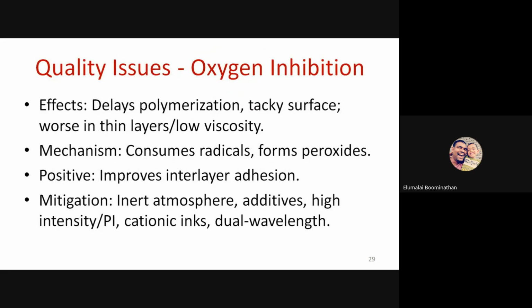And the oxygen inhibition, as we already discussed, is also an issue. When you use UV curable resins, the oxygen in the environment can slow down, sometimes even prevent the polymerization of the UV curable resin. So usually the oxygen inhibition issue is a two-edged sword. Sometimes it is positive in the sense the oxygen inhibition reduces the polymerization process of the layer. So the next layer will have a better bonding.